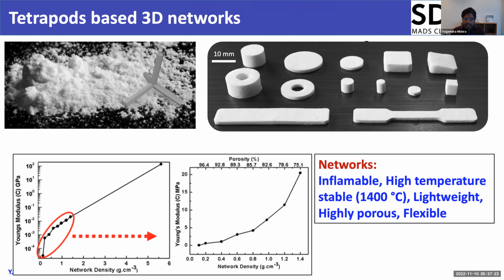Well, we have been doing this for the last 12 years, growing tetrapods, growing three-dimensional interconnected networks. And that's a small conclusion here. I would also like to comment that due to the C-axis growth, the hexagonal wurtzite crystal structure, zinc oxide is a very robust material in terms of growth. Doesn't matter if you mix two solutions in your kitchen, you will probably end up with some kind of zinc oxide nanostructures.